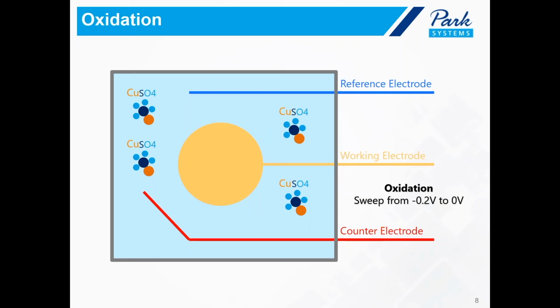When the positive sweep occurs, more and more copper leaves the gold thin film surface. What we will see in the subsequent AFM images is that the gold thin film surface goes from being clean to being crowded with copper particles, then back to being clean again. This indicates that the CV curve I have shown earlier is a totally reversible process.